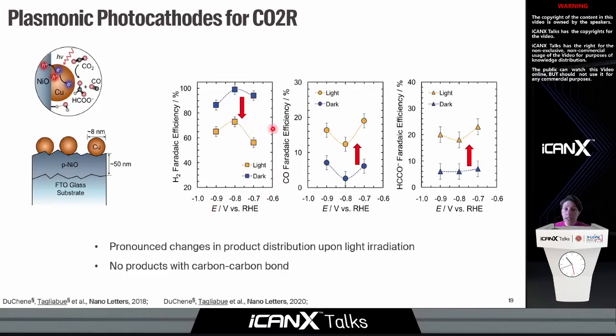And so again, we see that under illumination, we reduce the generation of hydrogen, and we enhance the generation of carbon-based products like carbon monoxide and formic acid. So again, the presence of these plasmonic nanoparticles entails a system with a selective capability of driving the CO2 reduction reaction over the hydrogen evolution. At the same time, we were not able to observe carbon-carbon products, which is what we were hoping for. And this suggests that there might be other trade-offs between the possibility of transferring an electron to the adsorbed molecule, as well as inducing a faster desorption, for example, of carbon monoxide, which is the intermediate molecule that is needed to create more complex products such as ethanol.